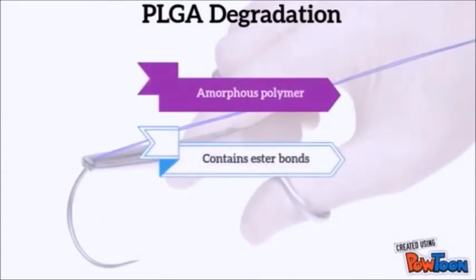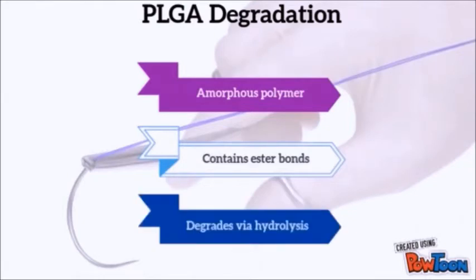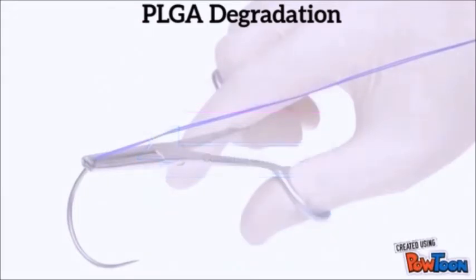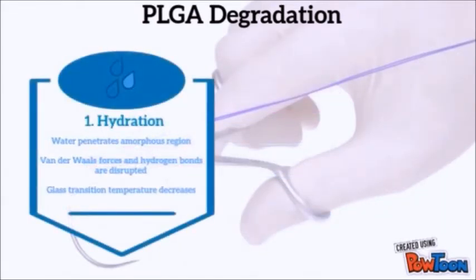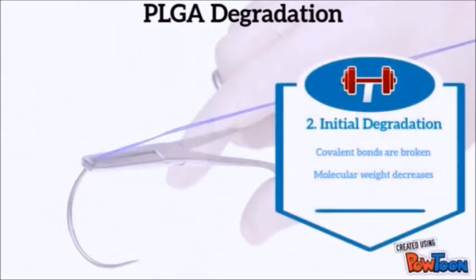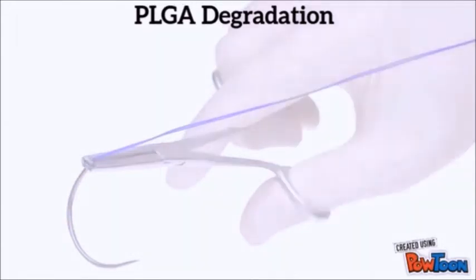PLGA sutures undergo bulk degradation via hydrolysis of the ester bonds within the polymer backbone. This process can be described in four main steps. Step 1 is hydration, where water penetrates into the amorphous region and disrupts the van der Waals forces and the hydrogen bonds, causing a decrease in the glass transition temperature, which makes the sutures more flexible and allows water to enter the structure more easily. Step 2 is the initial degradation. This involves cleavage of the covalent bonds with a decrease in the molecular weight.